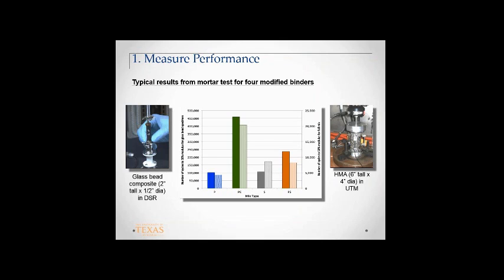to the same conclusion? This is Nelson Gibson's work using the viscoelastic continuum damage model with the fatigue damage test and the CNS parameter. So this is all of that. Richard Kim, basically Professor Kim's work that he developed over the years on the viscoelastic continuum damage model, is being put into this test method. Our test also uses the same model that he has, and we have since integrated healing and fatigue in the same test. So you don't run a sample for fatigue and a sample for healing. You use the same test to get healing, fatigue, everything. But the theory is the same as Professor Kim's.